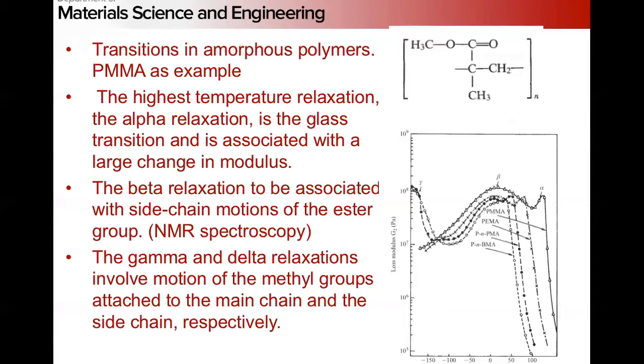Generally, the trend is that as we go down in temperature, the relaxations that we see tend to be associated with smaller and smaller interactions. This ester is larger and bulkier, and gives you more steric hindrance than these small methyl groups, right? And this is loss modulus here.